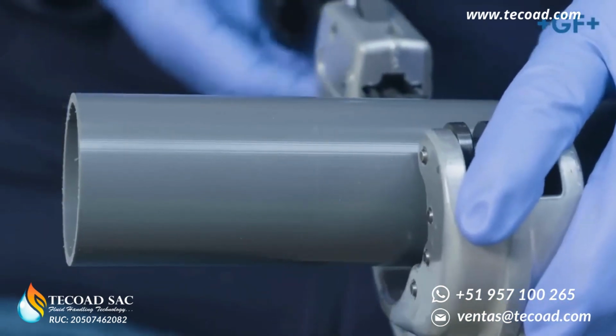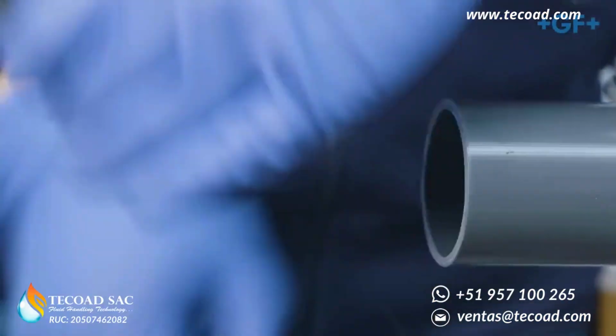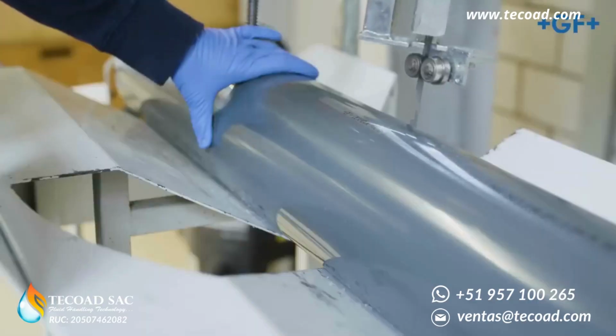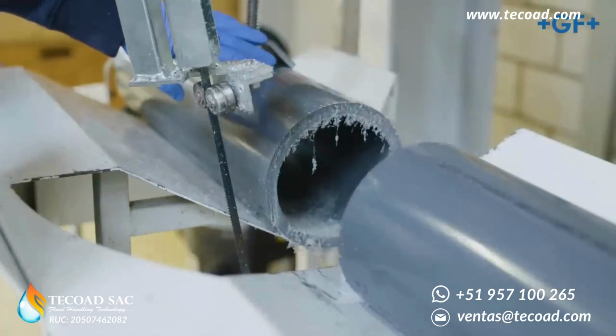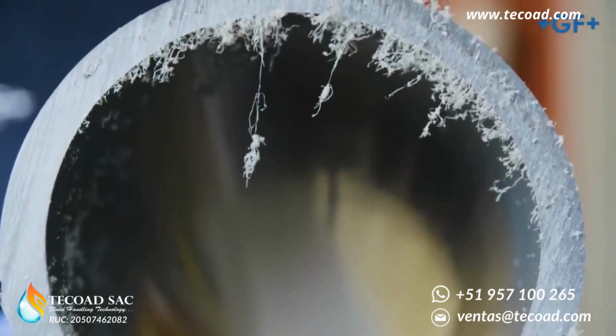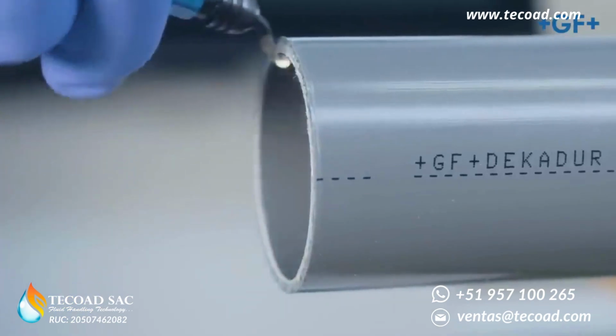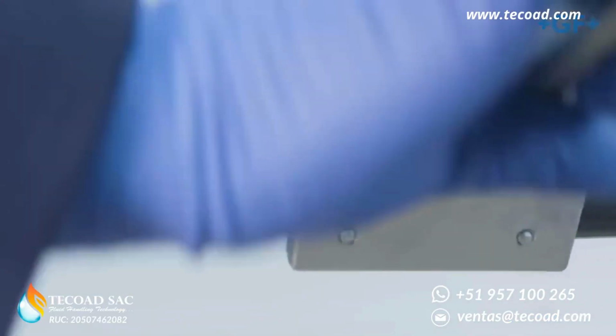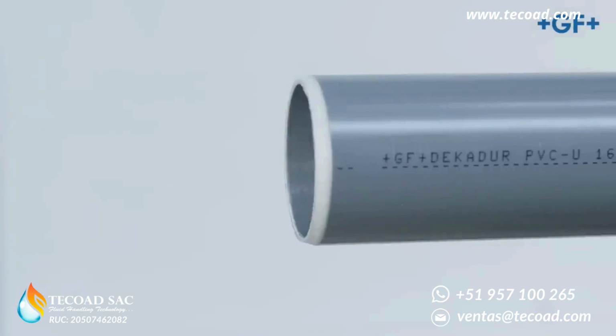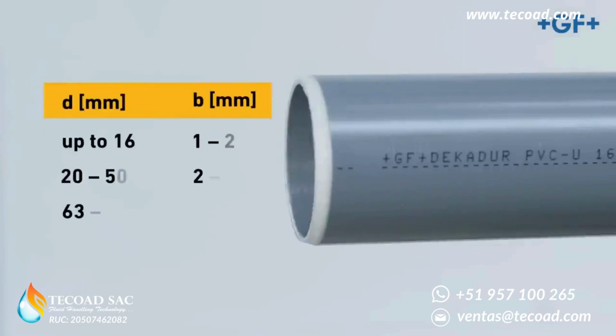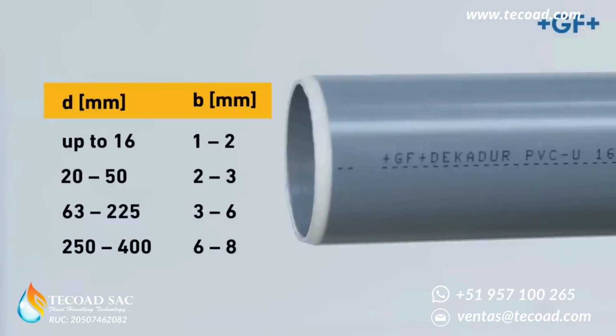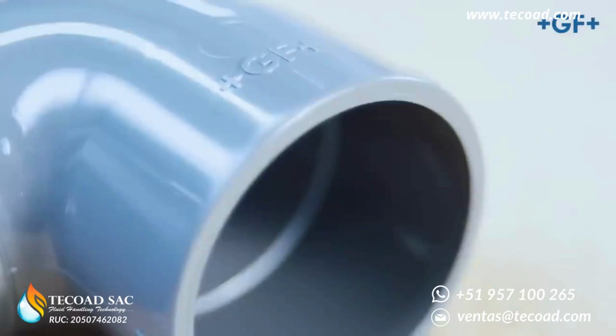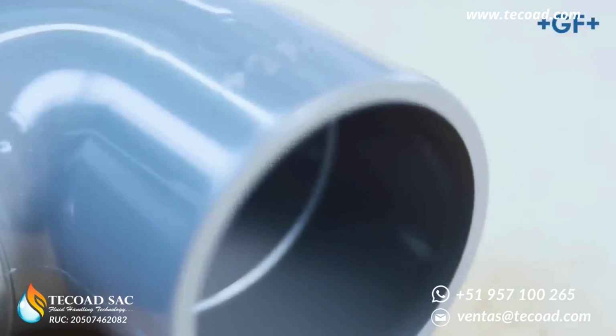Square-cut pipe ends are a prerequisite for a perfect cement joint. For bigger dimensions, sawing systems can also be used. Deburr the pipe ends on the inside if necessary, and chamfer the outer pipe end to ensure that the cement can penetrate evenly between pipe and socket. Chamfering is carried out with a pipe diameter of D20 to D50 at 2 to 3 millimeters in length, with pipe diameters of D63 to D225 at 3 to 6 millimeters in length. All GF fittings feature a pre-integrated chamfer.